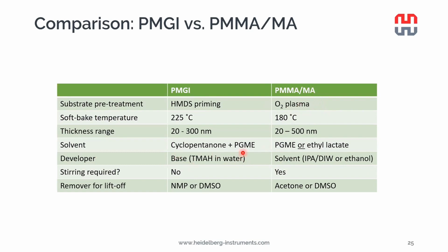Developer for PMGI is a base, a water solution, while for the PMMA MA we can use either ethanol in the water-free process, or a mixture of IPA and DI water also works very nicely. For both of these materials, we recommend DMSO, dimethyl sulfoxide, as the remover for the lift-off process.